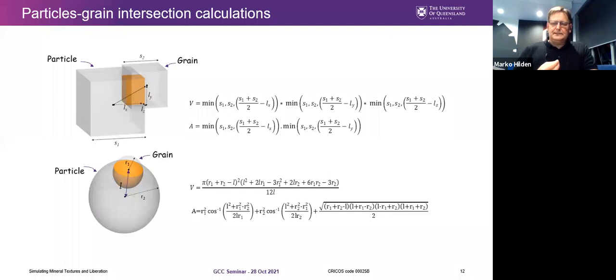And therefore, to calculate a particle, it's necessary to calculate the intersection volumes and areas with all the other grains. And from this, we can calculate the composition of the particle. These equations are known for orthogonal cubes and spheres. So therefore, those are the shapes that the model uses.